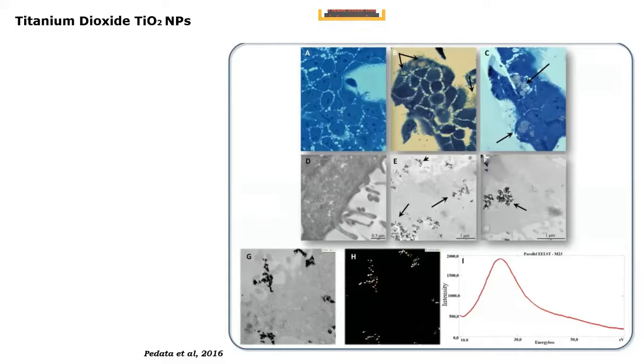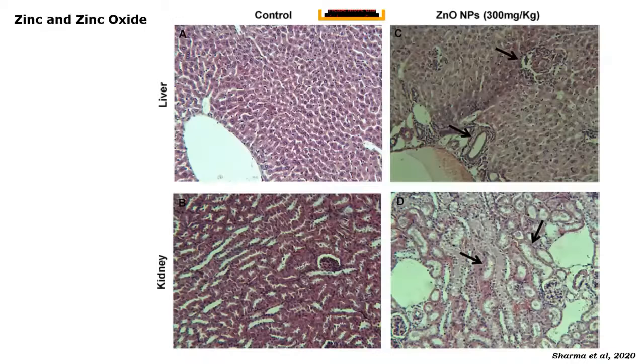This is a TEM image where you see how they are interacting with CACO2 cells, and they accumulate, so aggregation is happening, and then leading to regions of cell death. Zinc oxide is also the same. I will not go into detail, but you see regions with zinc oxide nanoparticles above certain concentrations creating some kind of toxicity effect.